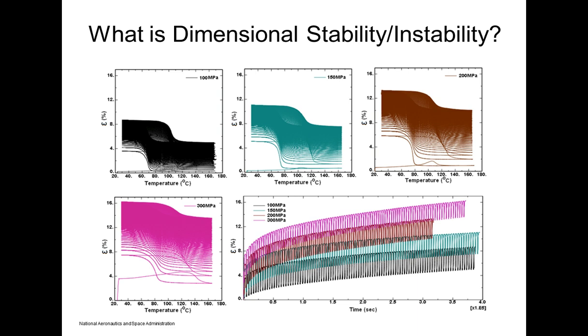There are alloys that we do for bearing class materials that can handle, now this is superelastically, on the order of about 3.5 gigapascals and about 4% reversible deformation in their austenitic state. We have actuation systems that we know of with some of the ternary alloys that we're doing and developing here within our group that can